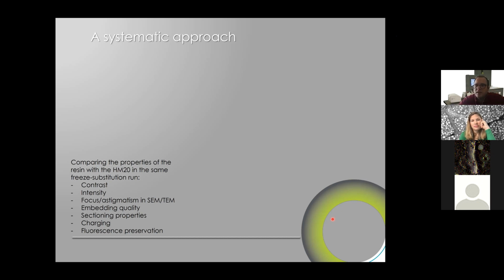How do we do the focus and astigmatism in SEM? In TEM it is not that relevant, but for SEM, you will see later on that this is one way of evaluating. We wanted to evaluate the embedding quality. This is quite important because if you have a conductive resin but the embedding is bad, you can't do anything. Sectioning properties, because as I was saying, I did that on the microtome, so I did a lot of sectioning.